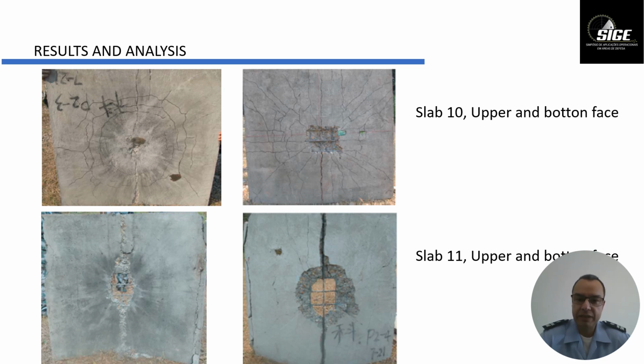Here is slab 10, upper and bottom face, in the first line. We can see that on the upper face, where the shock wave hit, there are some cracks similar to the paper we saw in the previous slide. And in the second line, we can see slab 11, the upper and the bottom face, and we can see that the damage was higher. We are going to see in the table why these damages are different for the same test.